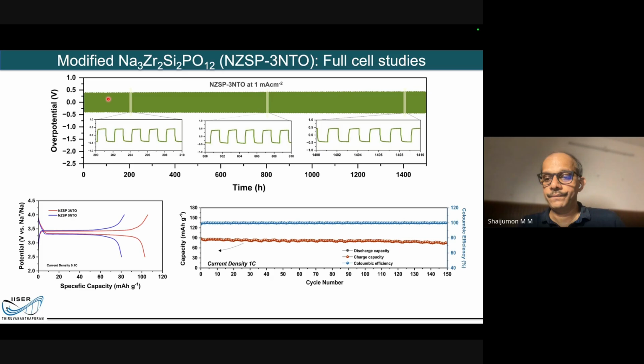We keep the solid electrolyte at the middle and then keep two sodium electrodes at both ends and cycle it. What it means is that the sodium is set to go through this electrolyte, come to this side, and then go back through this electrolyte. So how good and how long this can go without any variation in the potential, that's what we call the critical current density.